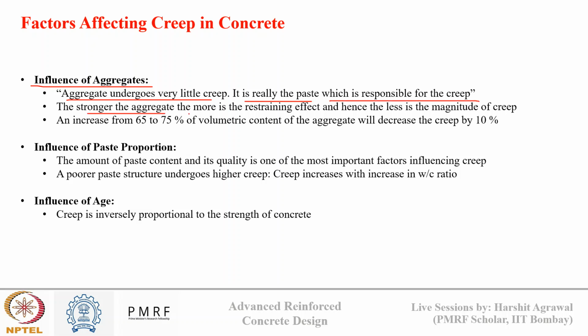So if we have stronger aggregate, we have less magnitude of creep, and if we increase the aggregate proportion from 65 to 75%, the creep can decrease by 10%. That has been found in literature. Influence of paste: if we have more amount of paste, there is a chance that it can undergo higher creep. So creep increases if we increase the W by C ratio.